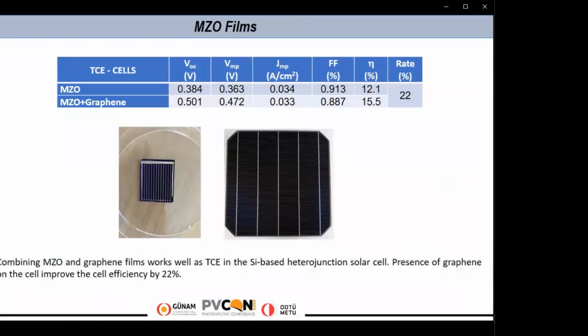Most parameters are reported for solar cell efficiency, such as fill factor and open circuit voltage. Fill factor was decreased in the MZO graphene hybrid structure. This is related to graphene having high sheet resistance, because high sheet resistance can limit fill factor. However, there isn't a serious decrease in fill factor.